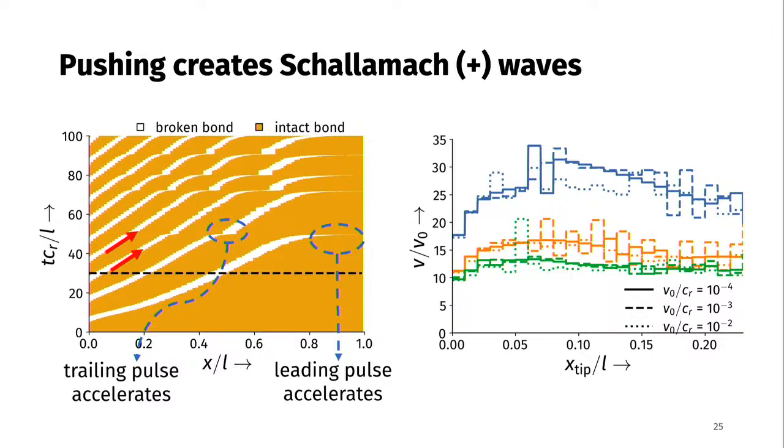This actually answers the question of what sets the velocity scale, because in the theory model we put in artificially that C by V naught was the actual scale, right? The applied velocity was the actual velocity scale. But now you see, if you plot this V by V naught as a function of various V naughts, again non-dimensionalized by CR, which is a constant, for over 2 orders of magnitude, the values don't change, right?